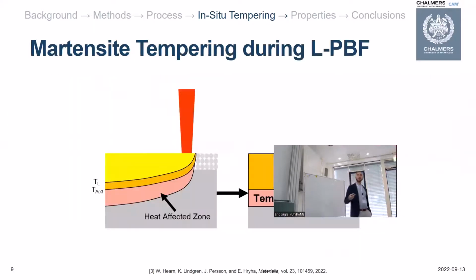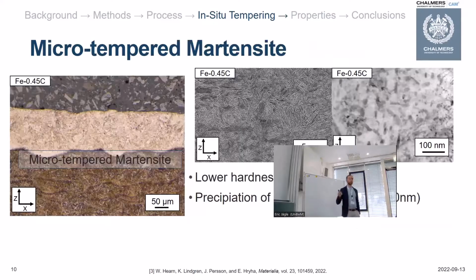Now, to look at what's the tempering that happens during the process, we found that the biggest change in tempering happens just below where your untempered martensite forms, within the heat affected zone of your melt pool. As it makes sense, everything that's heated below your stability temperature of austenite will not reform into austenite and will instead become tempered. In a similar way, we looked at the regions just below the top layer. And what we see already there is a substantial decrease in hardness, depending on your processing parameters. So instead of 800, you're between 400 to 500.